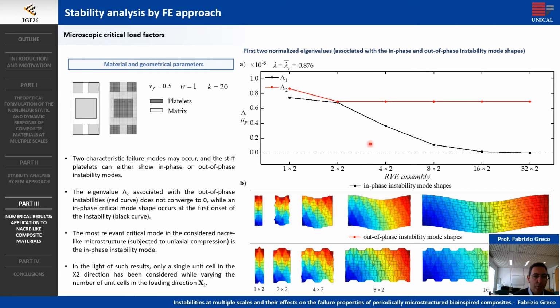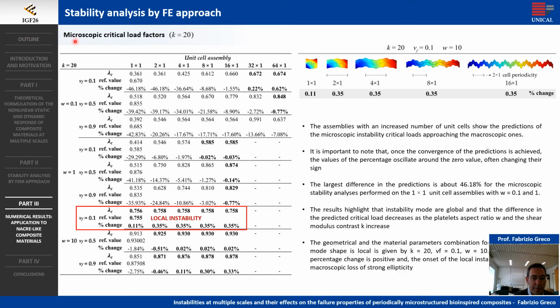The trends of the first, which is the lowest, and of the second eigenvalue are depicted for varying RVE sides in the x1 direction. The behavior of the lowest eigenvalue of the stability function shows that the prime instability mode is characterized by an in-phase pattern. The obtained microscopic critical stretch ratios are summarized in this table for each investigated unit cell assembly to compare the microscopic critical factors with the macroscopic ones.